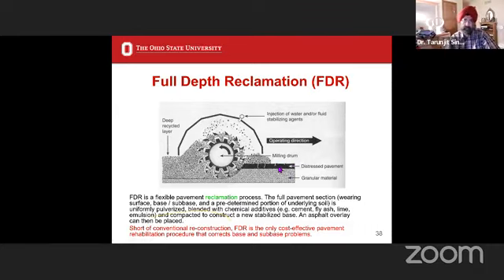Then what one essentially does is a very simple mechanism. It is an in-place full depth reclamation in which we use some sort of a grinder, in which we take all of the distressed pavement, or the base and the subbase that has failed. And if need be, if we need some finer materials, we can increase this depth further below, as has been done, you can see. We add some lime or lime kiln dust, some pozzolanic material, add water, and then behind this, this is called a rototiller. Behind this, there is compaction equipment that is coming to compact. So this is an in-place reconstruction of the road.